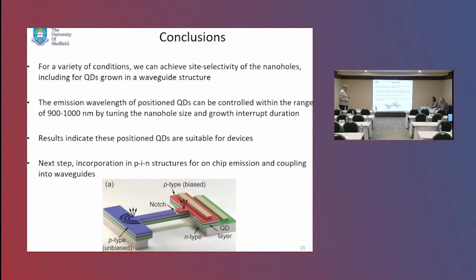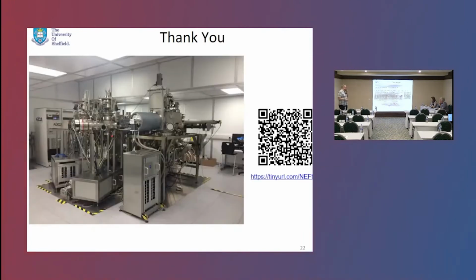So the next step that we have is to incorporate them into an active structure. So in this case, the top and bottom of the waveguide, we put P and N-type doping to make a diode so that we can inject that current I talked about at the beginning. And if we have a quantum dot over on this side, if we isolate the top by cutting into the P-type layer so that there's no conduction between the two, we then have an emitter which can launch into the fiber, into the waveguide, and then scatter out through the top. So again, a simple initial experiment followed by emission into more complicated structures.